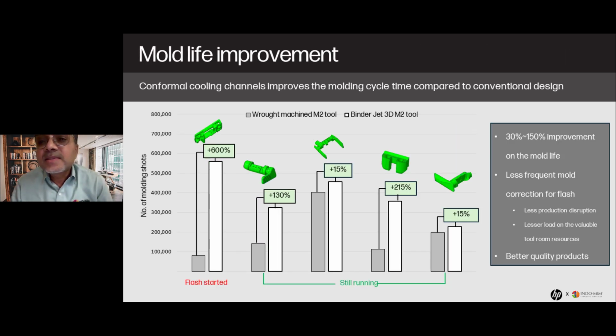And for us, the biggest surprise also was the mold life improvement. We thought there could probably be a 20-30% improvement in the mold life. And that was a huge requirement for us, because when you are running 1,200 molds in a year, and you produce 900 molds, and when you support 12,000 programs, there is always a requirement of replacement molds. If the molds are wearing often, that will put a lot of burden on the tool room, and then you just keep investing in the tool room, which is not productive at all. So we were able to see, in fact, on one of the components, as you see here, 600% improvement in the mold life.